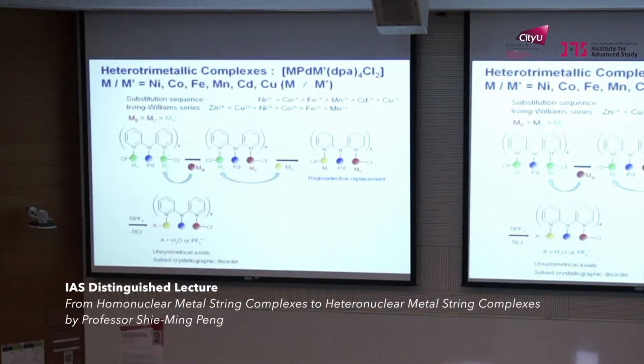Furthermore, we can use a third metal ion to substitute the terminal one, to become ABC or ACB. We studied this seriously, and the substitution sequence is that nickel can substitute cobalt, which can substitute iron, manganese, cadmium, and copper too. And in coordination chemistry, the very famous Irving-Williams series shows the stability, including thermodynamic stability, of metal compounds in this series. Okay, we are consistent in this way.